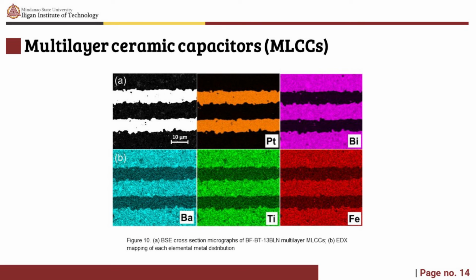Now for the MLCCs, or multi-layer ceramic capacitors, figure 10a shows the BSE cross-section micrographs of BF-BT-0.13BLN multilayer MLCCs, and figure 10b shows the EDX mapping of each elemental metal distribution. Ceramic capacitors of BF-BT-0.13BLN were fabricated with dielectric layers with an active electrode area of 5 mm squared to increase the BDS and energy storage properties, as shown in figure 10a and b for this study.